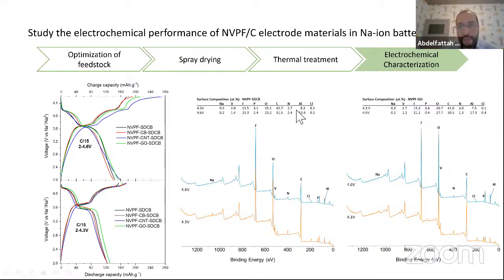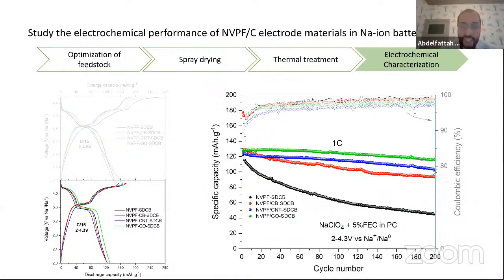And also we have some reaction with aluminum, which is used here as current collector, which means we have some side reaction of the electrolyte and active cathode material at high voltage. This is why we were thinking to make cycling only until 4.3, and we can see that for almost all materials we have only the theoretical capacity, and mainly the one with graphene oxide before grinding has very good stability over 200 cycles.